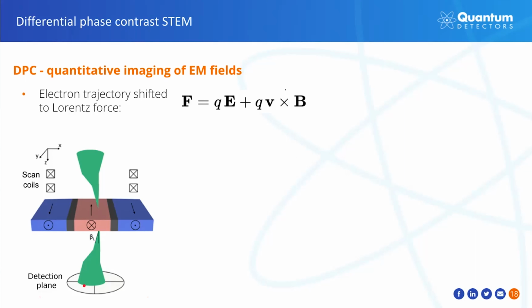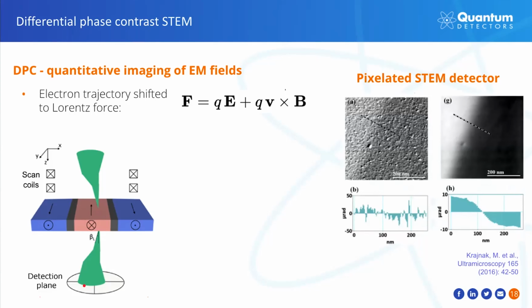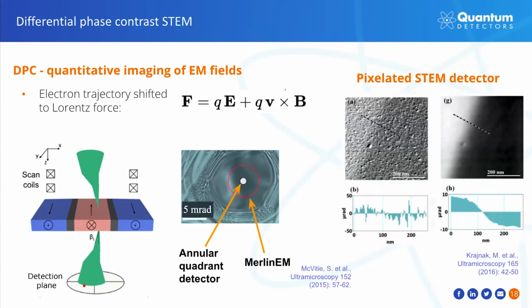I've shown that utilizing a pixelated detector can greatly enhance the signal to noise, but this is not the only advantage. Because we can detect the position of the beam in post-processing with much better sensitivity, we're able to expand the practical resolution of the microscope itself. This was previously limited by the sensitivity of the segmented detector to around 5 nanometers. Utilizing MerlinEM, we were able to achieve better than 1 nanometer size probe. And this is basically the same instrument. It was always capable of doing this experiment, but replacing the detector was the key.